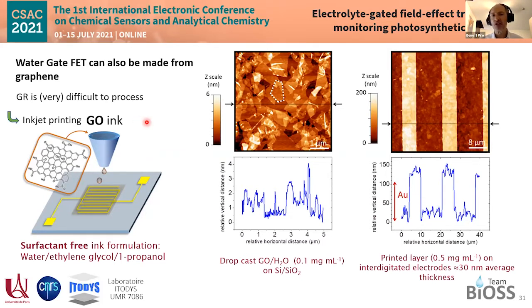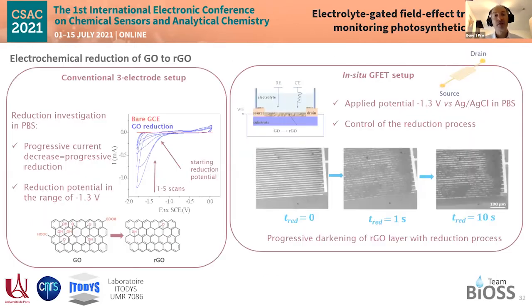And because graphene is not easy to process, we use graphene oxide and even a graphene oxide ink that we inkjet print. So we needed to engineer that ink, but we succeeded to inkjet print graphene oxide ink, stable, homogeneous, etc., on our interdigitated source and drain device, the transistor. There are some pictures, but I have no time to discuss that, but just to show that it's not, of course, a single layer graphene, it's several layers. On top of it, it's quite homogeneous.